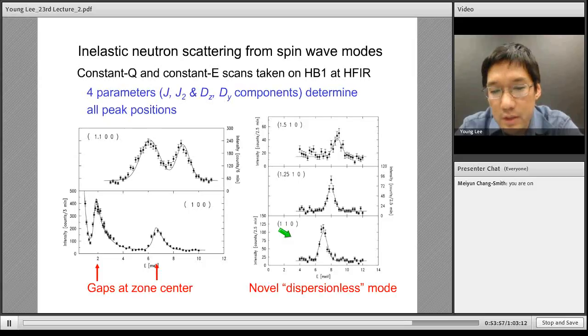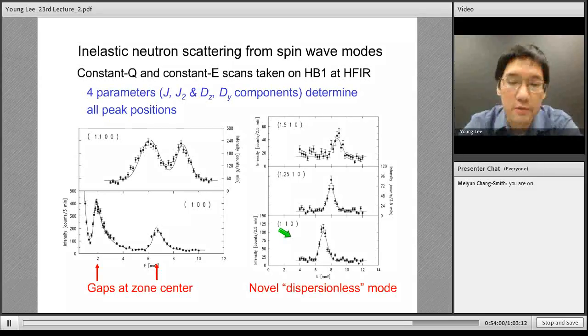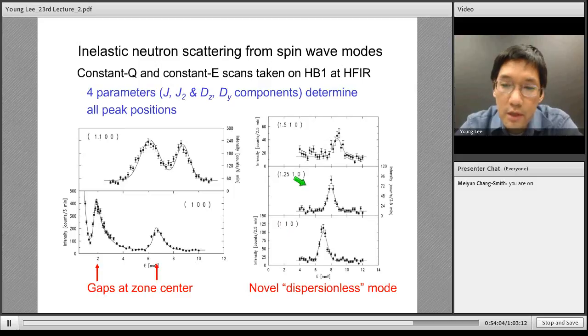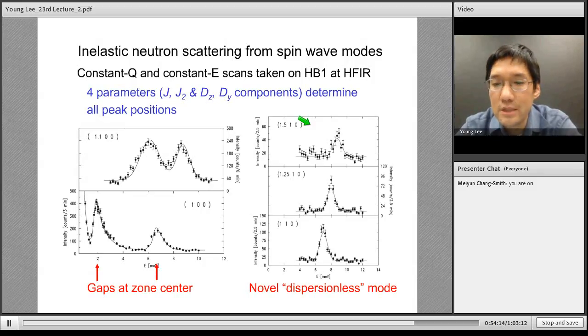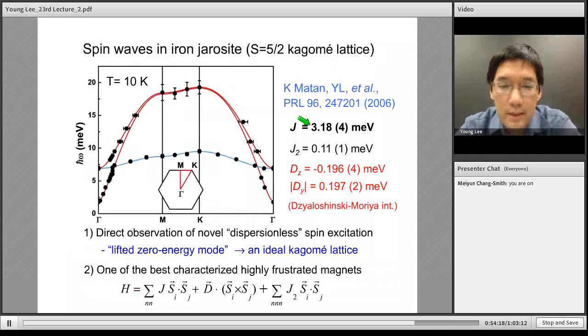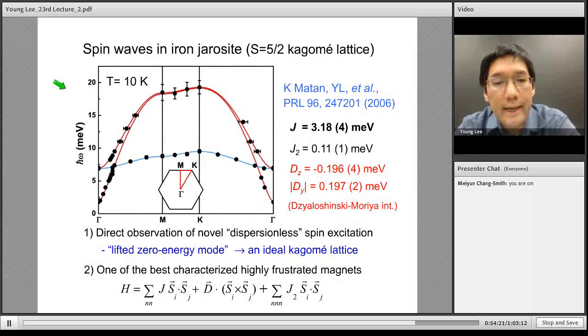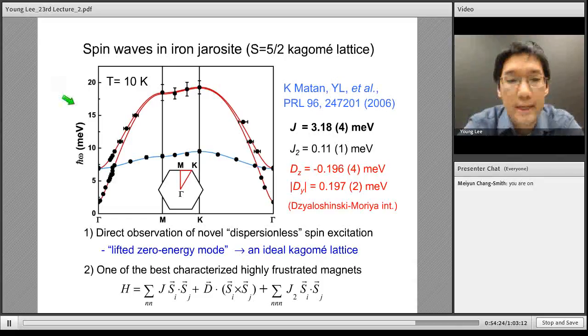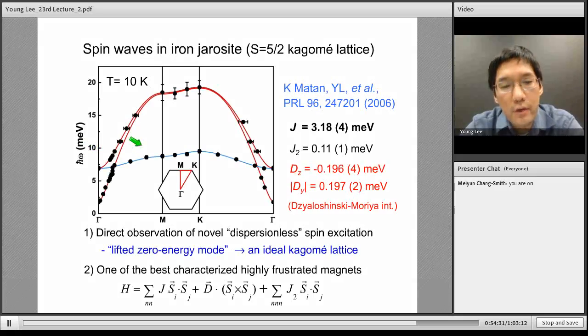But what was very interesting was looking over in this right series of panels. So 110 is another zone center, and then as you go out to the zone boundary, you see that this peak has not really shifted all that much. It's nearly dispersionless. It's a very flat mode, and that was very interesting to us. So when we put all of our data on a dispersion plot, we can see that we do have dispersive modes, and those are shown in red. But what was very exciting to us was this blue mode, which is extremely flat. It goes from some zone center energy, and it doesn't disperse to a high position at the zone boundary, but it stays at a very low energy.